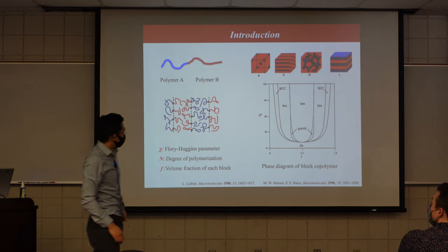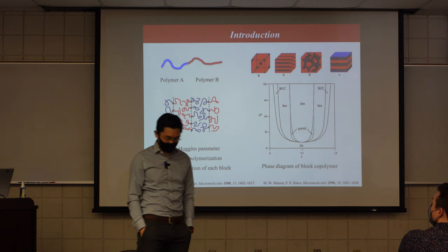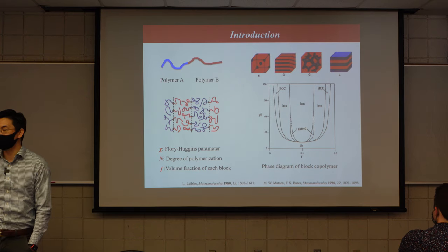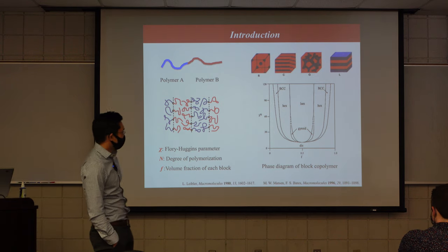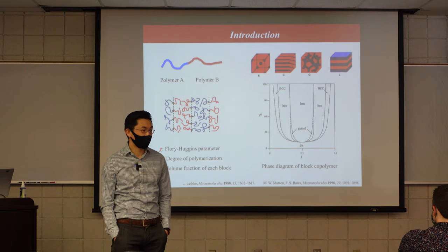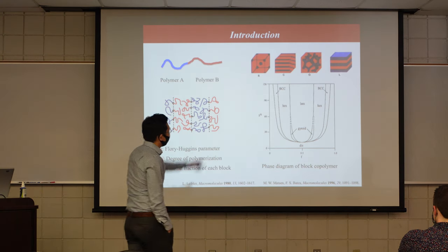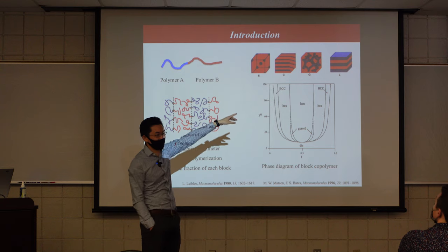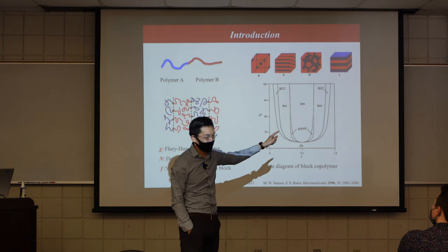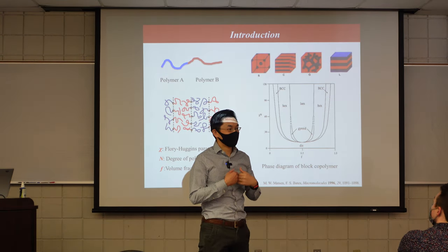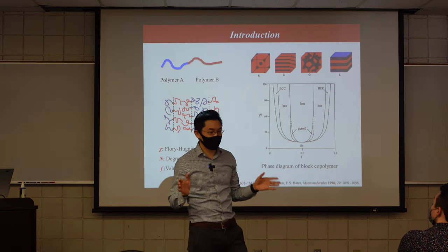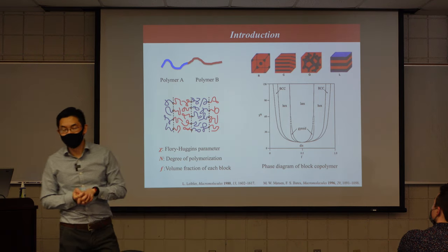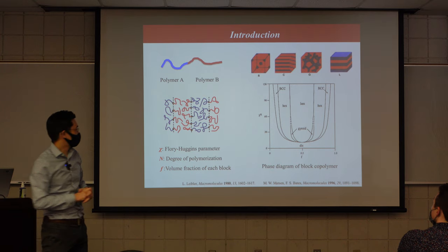More recently, people have found easier ways to repeatedly manufacture gyroid structures. Professor Rong-Ming Ho in Taiwan is a good person to look for. He played with a lot of polystyrene, polylactic acid to self-assemble those gyroid structures. And they're actually pretty cool images. If you could assemble them and etch away these blue blocks, make them void, you can degrade PLA in acid. You leave a polystyrene porous matrix. You can backfill with any other nanomaterials and throw away the polystyrene. Think about it like a die cast, you can remove the die and then you are left over with any gyroid metal structure. He did a lot of those works, looks very nice, impressive.